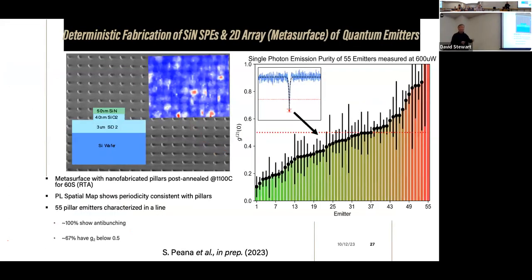But the main point I'd like to make here is that for conventional single photon emitters in solids, which you obtain, for example, by thermal annealing or ion bombarding, as I mentioned, they are kind of random. They are controlled by a Boltzmannian process, and the probability to get single photon emitters is about 30% at most. Here we are clearly above that. So therefore, we believe it is a deterministic process, and it could be further optimized.